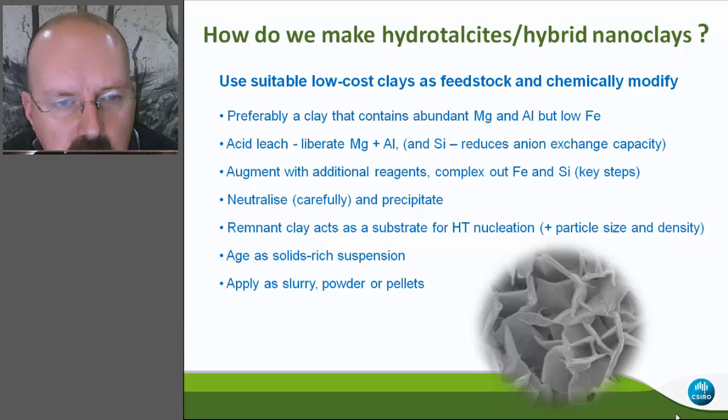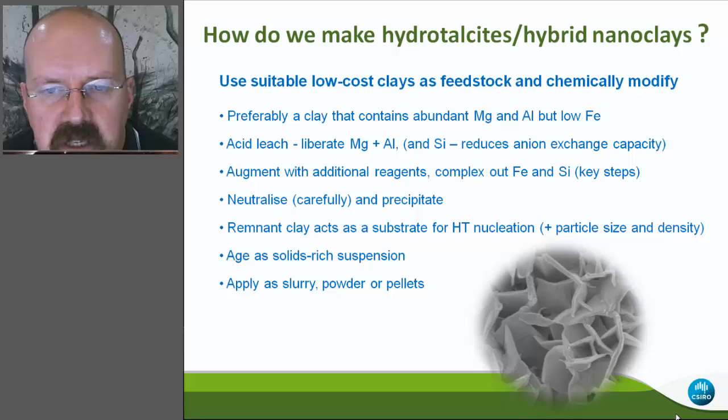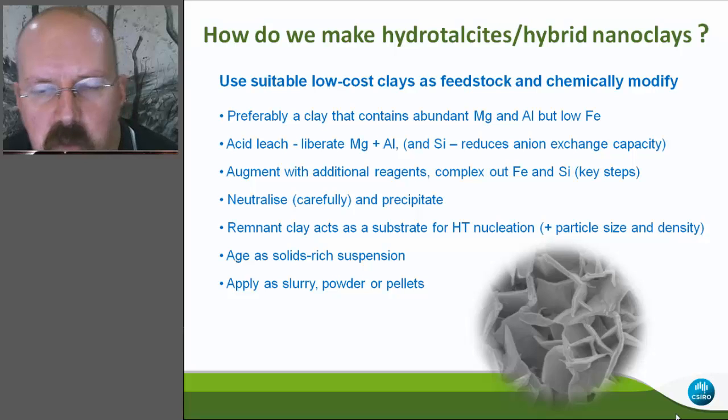We also carefully neutralise the nanoclay, which is very important for precipitation of the hydrotalcite. Importantly, one of the reasons we also use clay is that those remnant clay layers actually act as a substrate for the hydrotalcite nucleation. This is where the concept of a hybrid nanoclay came from, that we use a clay and then we precipitate the hydrotalcite. The remnant clays are also important because they add particle size and density, so that assists where we want to see settling of these hybrid nanoclays in an aquatic system.